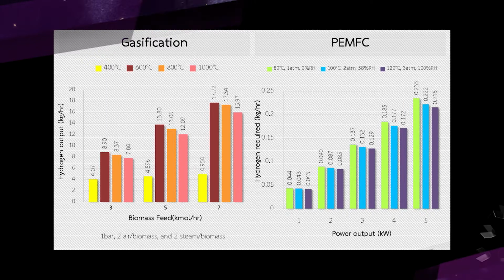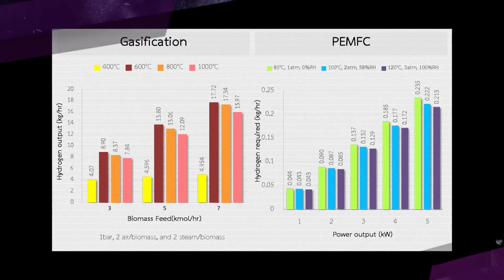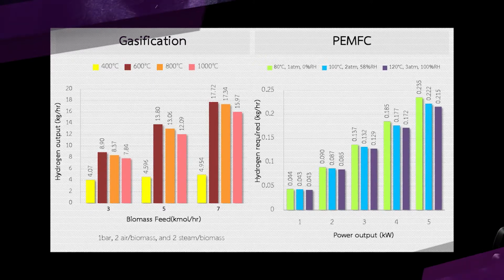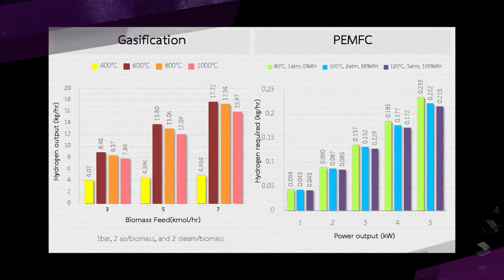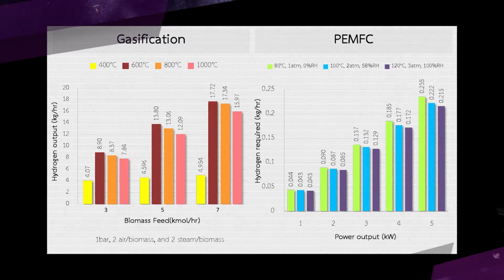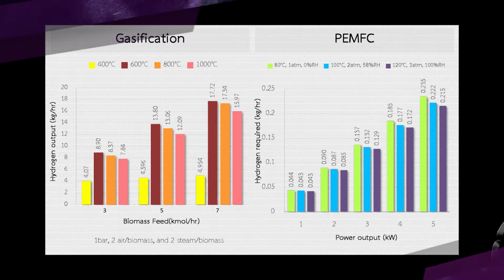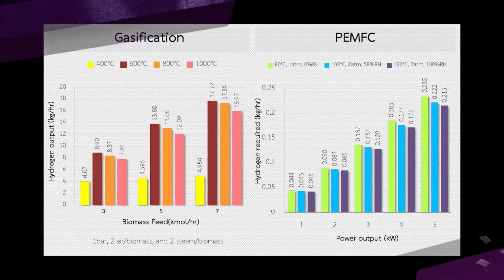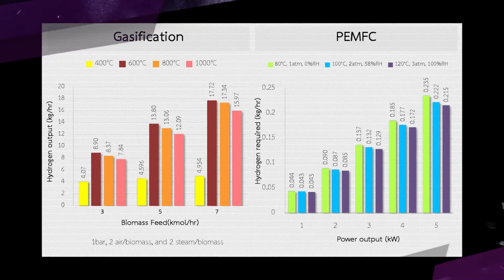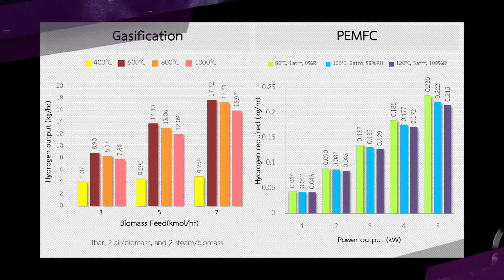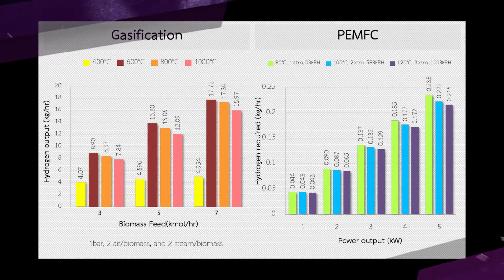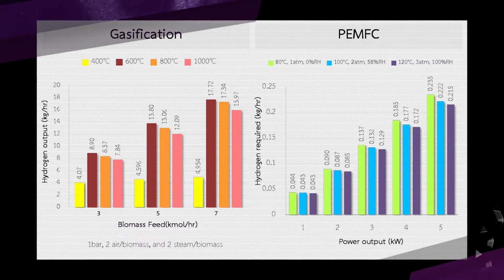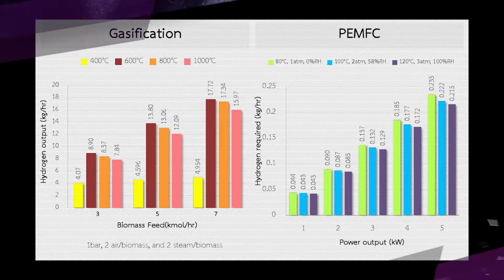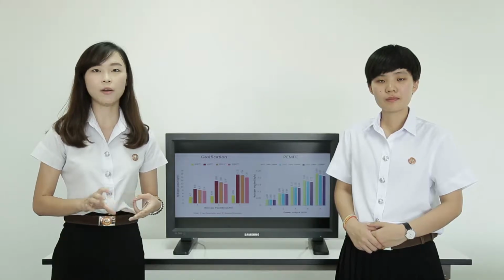For the PEM fuel cell part, we set the power output of 1 to 5 kilowatt and operate it at 3 different conditions. First, at 80 degrees Celsius, 1 ATM and 0% RH. Second, at 100 degrees Celsius, 58% RH, 2 ATM. And lastly, at 120 degrees Celsius, 3 ATM and 100% RH. As we can see from the graph, as we increase the operating conditions, the amount of hydrogen required decreases. Therefore, the best condition, the one that requires the lowest amount of hydrogen, is at 120 degrees Celsius, 3 ATM and 100% RH.